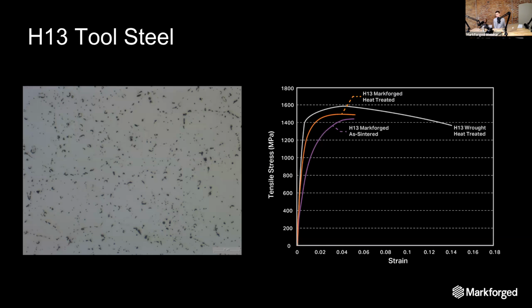So generally what you do is you temper, or even double temper, the steel afterwards. The temperature you temper it at, a nice little alliteration there, has a pretty heavy control on both the toughness of the steel, so how much bend, how much malleability you're going to get, and the hardness. What we recommend is about a 600 degrees C temper, and that yields the 45 HRC that you'll see on our data sheets if you've seen them before, and you'll see again if we are able to find it after the webinar, if Marco sends it out.